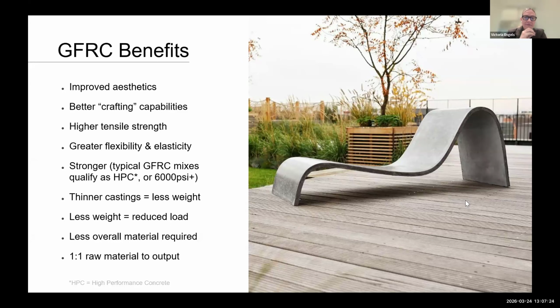The transition to that finer aggregate and the white Portland cement means it's going to have a smoother surface and a more highly decorative finish. But really where you're going to find the most benefits is on the inside of the product. Tensile strength and flexibility are improved with the addition of those glass fibers as well as the acrylic polymer. And this means that GFRC pieces are far less likely to crack when torque or pressure is applied.